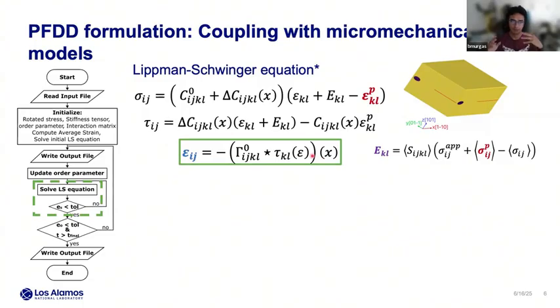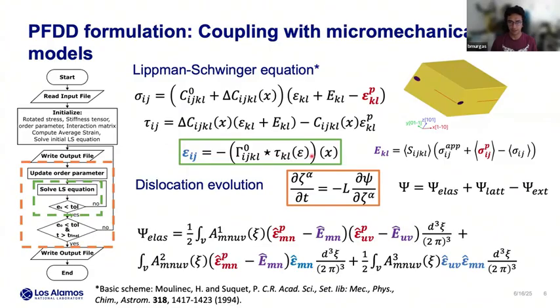And so what I'm doing is that I take this total strain and I use it to define the elastic energy for my phase field evolution equation. If I want to make the phase field evolve, I have to define these energy terms. In this case, we have elastic energy, a lattice energy that defines the resistance for a dislocation to slip in your lattice, and then the external energy. I use the total strain in the definition of the elastic energy, and the rest of the parameters of the energy terms remain intact. They are the classic phase field dislocation dynamics.